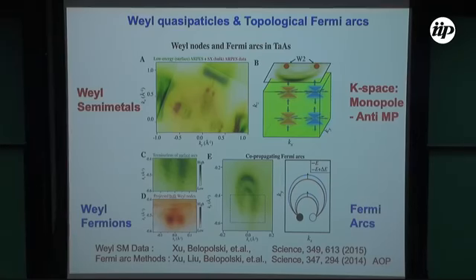Now you can see that when I presented the experimental data, I did not refer to any band structure calculation. I could have done that. But the experimental proof of the existence of Weyl node and Fermi arc, our proof, is independent of the calculation. We did not make any comparison to calculation. You can go and try to do calculation, but in the process, we also learned, because we can calculate these things, that since we don't know the surface potential very well for first principle calculation or DFT, you hardly find a real agreement. You'll see some sort of broad agreement, but the real agreement is difficult. So that is the reason I also avoided making a comparison and saying, oh, looks like the calculation, so we found something. So I gave a proof independent of calculation.